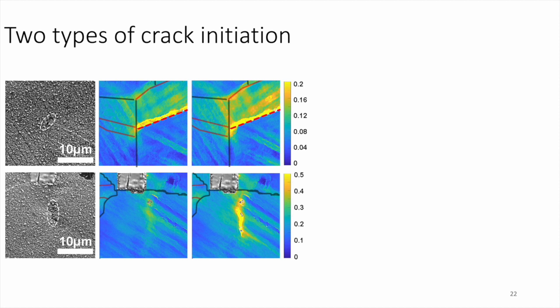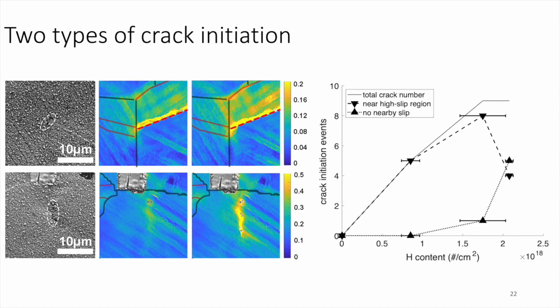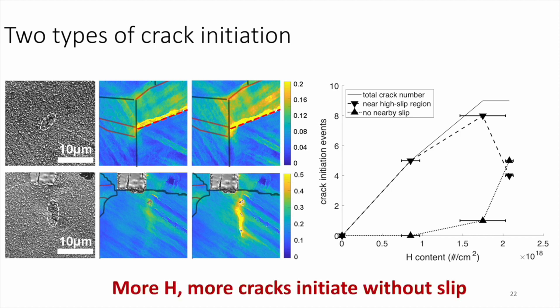So we count the type and number of these crack initiation events in each of the samples, and we plot this as a function of hydrogen content, as you see here. When there is no hydrogen, we didn't observe any crack, and as the hydrogen content increases, so does the number of initiated surface cracks. As for the crack initiation type, at low hydrogen content, all cracks initiate within the high slip region, and at the highest hydrogen content, most initiation events are not preceded by nearby slip. So that means with more hydrogen, more cracks initiate without slip. So what is the role of slip in this case? And can we even further quantify this?